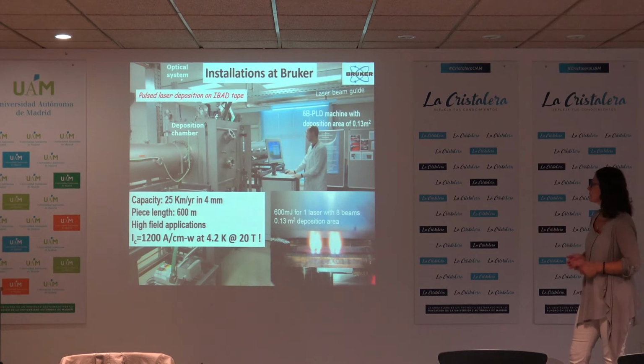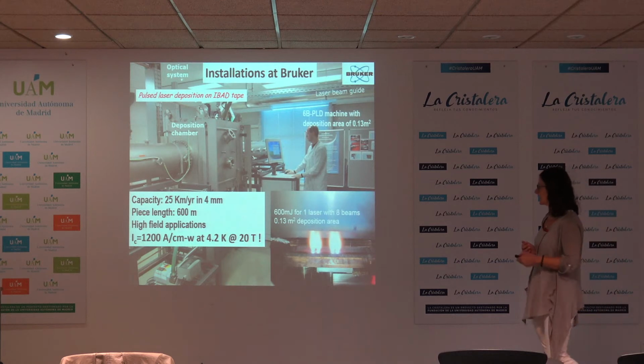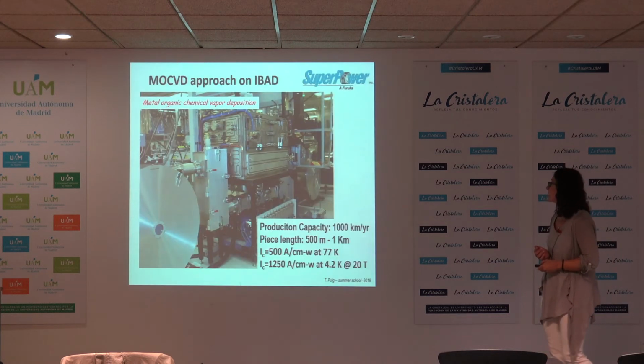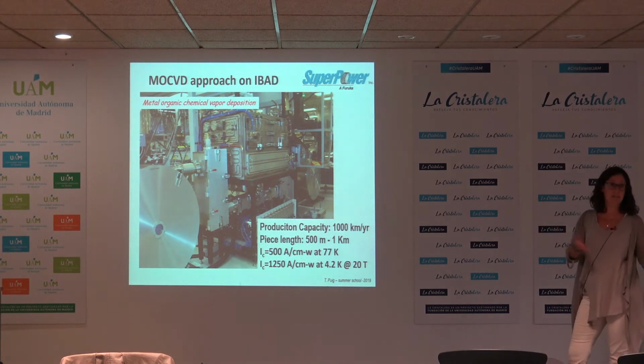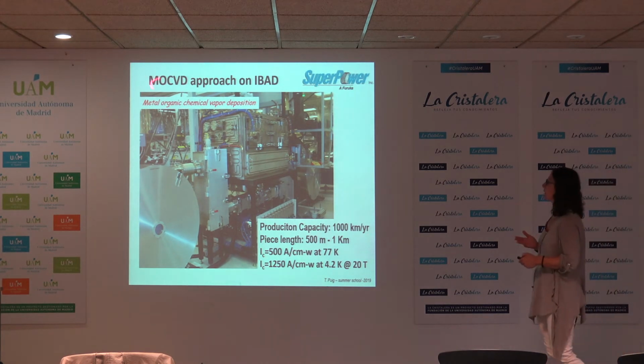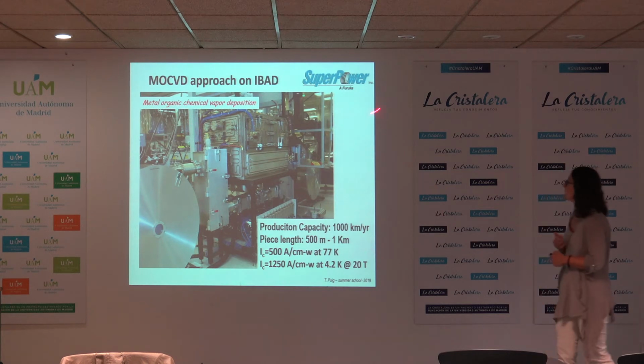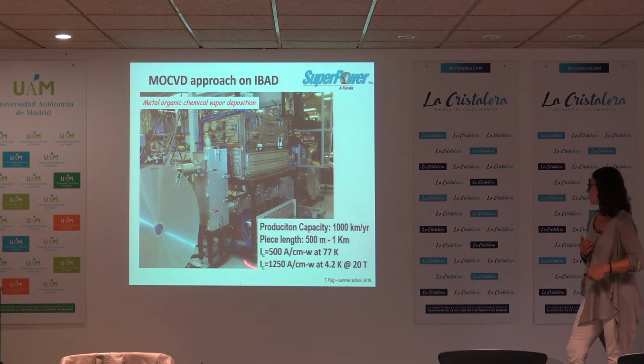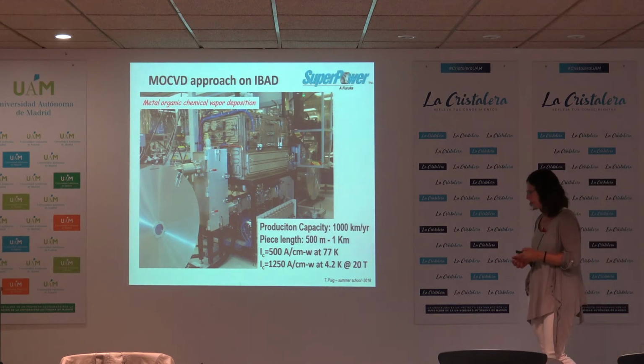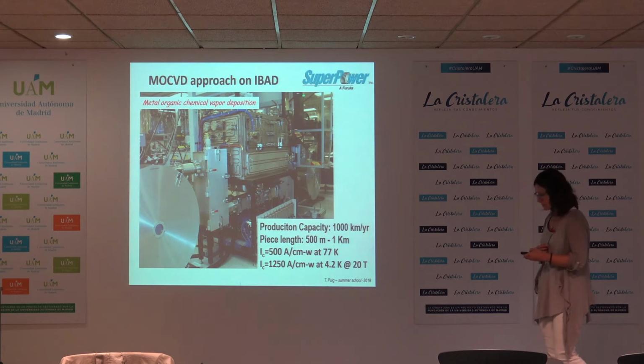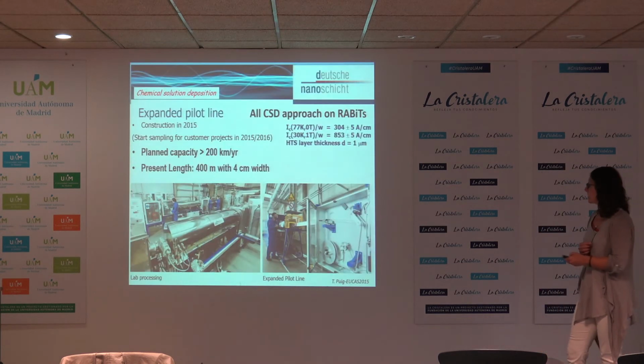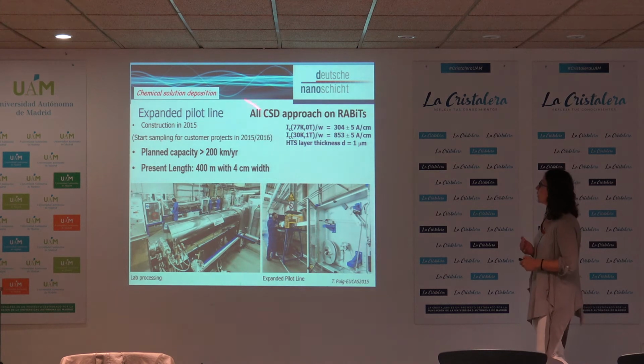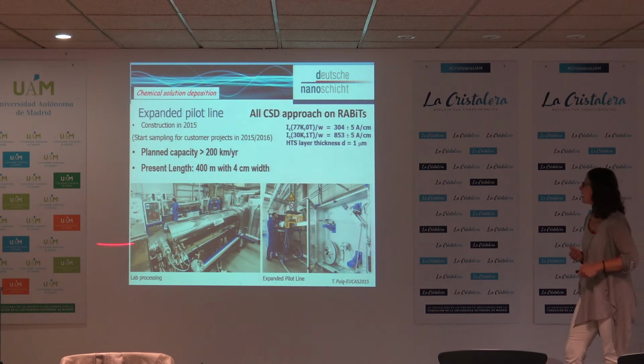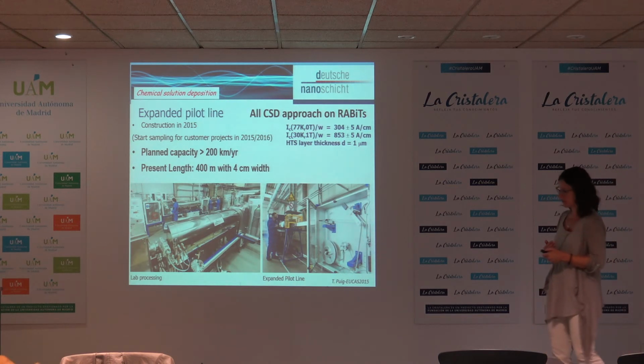This is Bruker, which is at this moment able to get 1200 amps at 4.2 Kelvin and 20 Tesla in pieces of 600 meters. That was by pulsed laser deposition. This is MOCVD, metal organic chemical vapor deposition, in US with SuperPower, also able to get over 1,200 amps at 4.2 Kelvin or 500 amps at 77. And then this is also in Germany, Nano. These are all using chemical solution deposition, which is a very low cost technique, able to get also over 300 amps at 77 Kelvin.